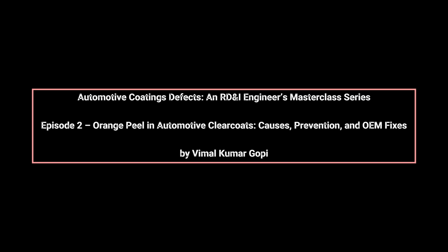Experienced RD&I engineers often implement seasonal solvent adjustments, such as slower reducers in summer and slightly faster solvents in winter, to maintain a consistent leveling window. Airflow across the panel is also critical. Excessive air velocity may dry the surface prematurely, while insufficient airflow can create localized pooling and uneven leveling.